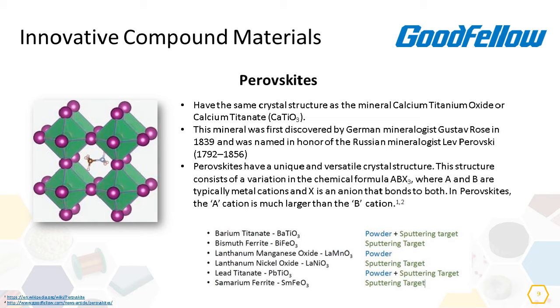I will discuss on this slide perovskites, which is another compound. It is a chemical compound. Perovskite materials have recently attracted significant attention as the most promising and efficient materials for optoelectronics and photonic devices. A perovskite material has a complex crystal structure, as we can see in the slide, and can be produced by combining two different cations. Perovskites are usually deposited, and they are called layer perovskites, and they are deposited as epitaxial thin films on top of other perovskites by pulsed laser deposition or molecular beam epitaxy. Thus, in our catalog range, you can find perovskites in two different forms, such as targets or sputtering targets, or powders. The complexity in their structure combined with the layer structure leads to tunable properties, and that's very important.